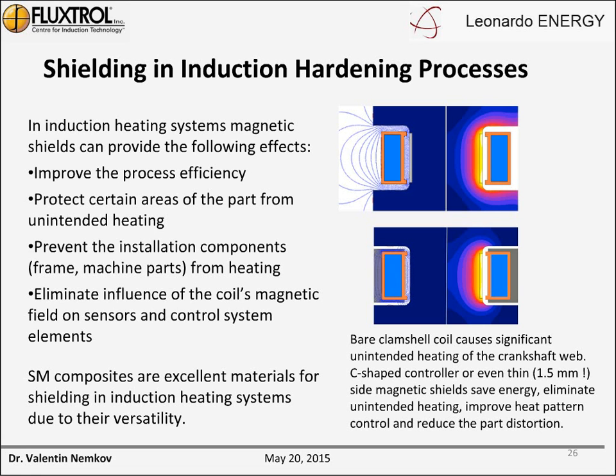If we apply a C-shaped controller, or even only a thin, about 1.5 millimeter, side magnetic shield, we can eliminate the unintended heating, improve heat pattern control, and reduce part distortion.